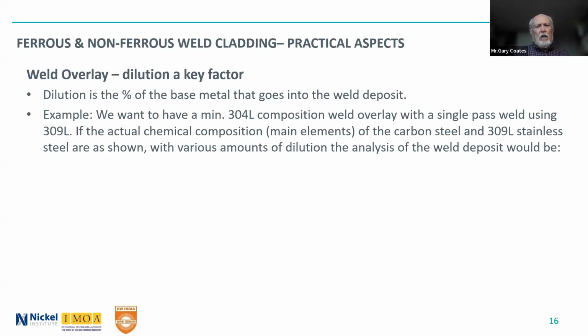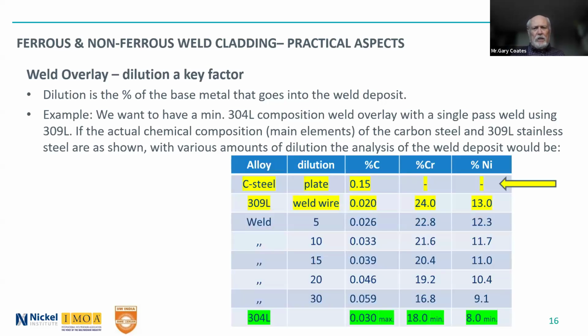You want the actual chemical composition, the main elements of the carbon steel and the 309L, and we'll show them here. So in the carbon steel, essentially of the three that we're concerned about here, it's only carbon, and I'm just taking a figure here, 0.15, and the stainless steel 309L weld wire, low carbon, high chrome, high nickel. So if you then say, okay, I can do a weld process that has only 5%, oh, sorry, at the bottom is the 304L composition. I didn't indicate the minimum chromium and nickel there, but we'll talk about that shortly.